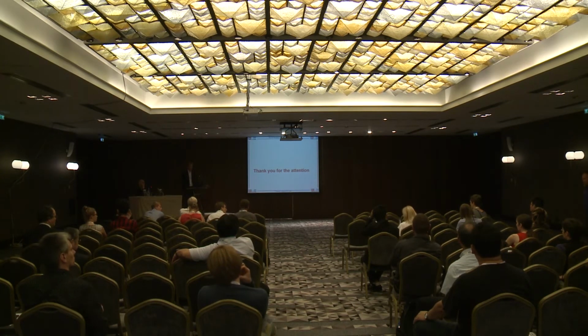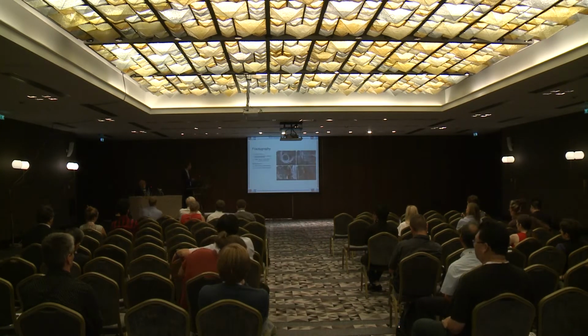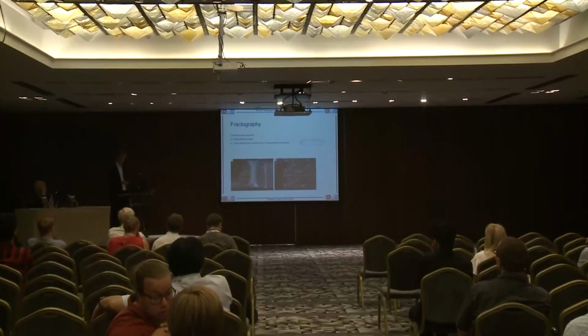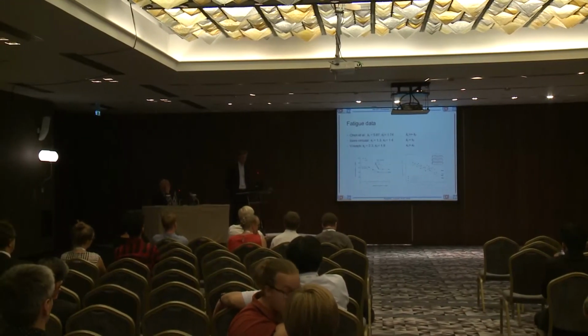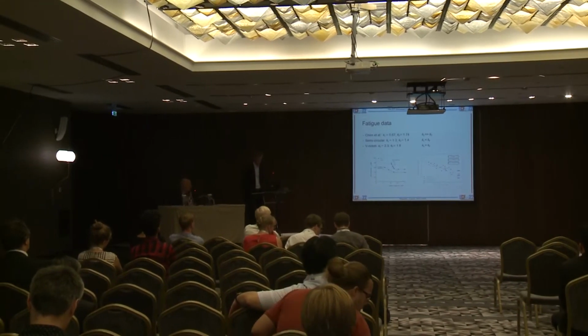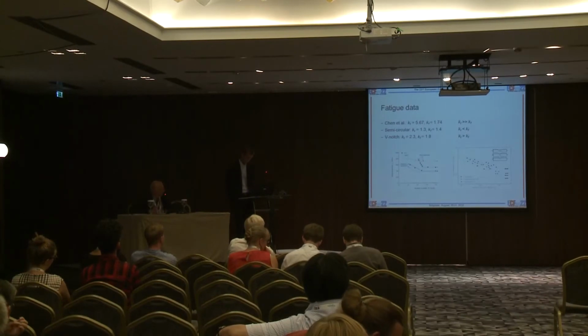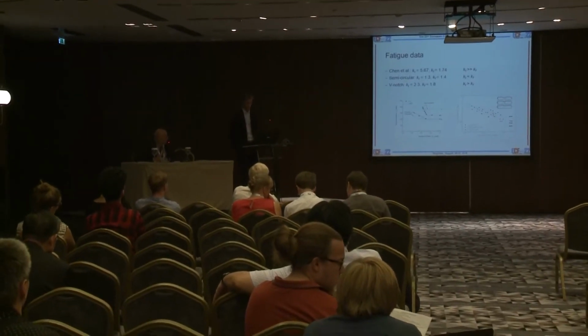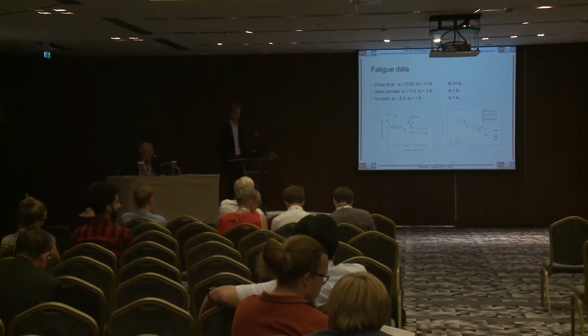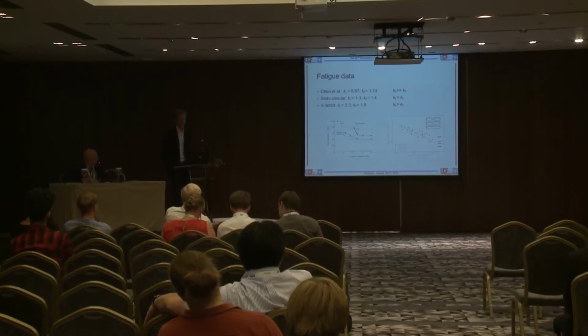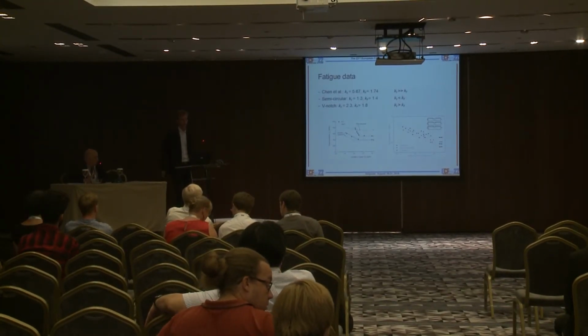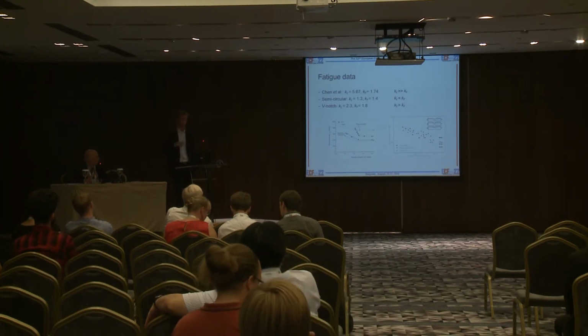Of the SLM-produced Inconel 718 with that of conventionally processed 718? Yeah, I have it here. So this one is the comparison. You see that the fatigue strength for the conventional one is around, let's say, 500 for the unnotched specimen, and this one is 250. But for data reported on conventional Inconel, it's always heat treated, and then you would have the gamma prime phases and these kind of things, which will strongly increase the fatigue life. But my specimens are only as built, so you don't have these kind of phases.